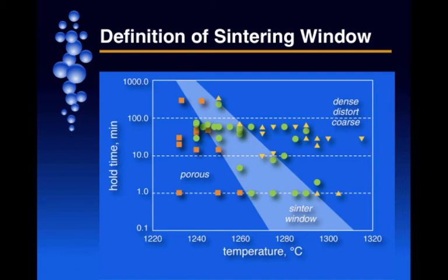In the case of liquid phase sintering, you can have more opportunity for distortion. And so these are some kinds of things. In addition, you could have weight loss, where volatile species begin to evaporate from the material, and so that results in lower densification and lower properties as well. Right? So there is a sweet spot, a time-temperature combination that might work well for each material.